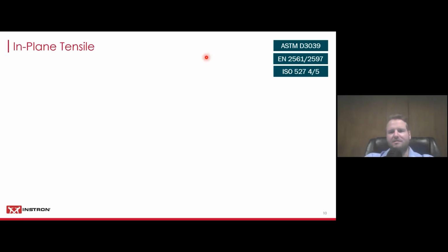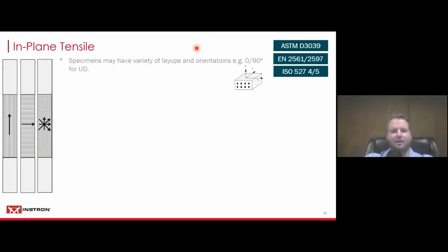So in plane tensile testing, most common standards we have here are definitely ASTM D3039 and ISO 527-4 and 5, but there's also a variety of more what I would call legacy standards that some people still test to. So like we established earlier, specimens can have a variety of layups with fiber orientations, either in the 0 degree and the 90 degree direction, or something more balanced like we've seen in the first video. So that's when you stack different plies on top of each other with different fiber orientations to get something that is more balanced and probably something that is much more realistic for end applications.